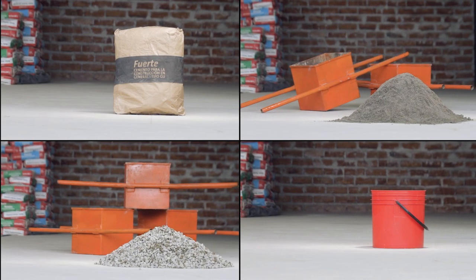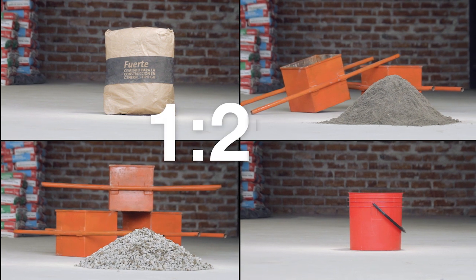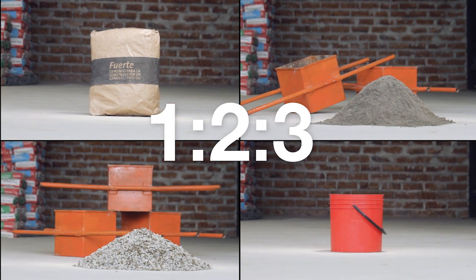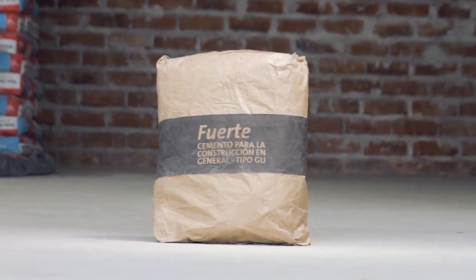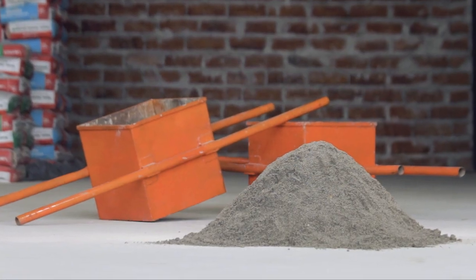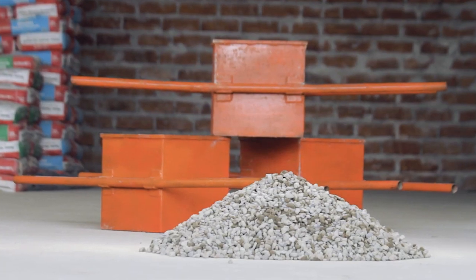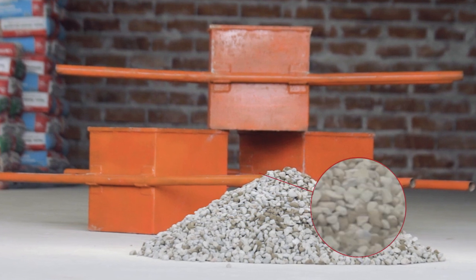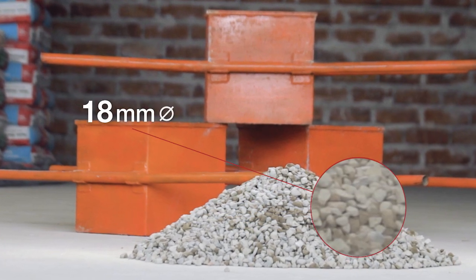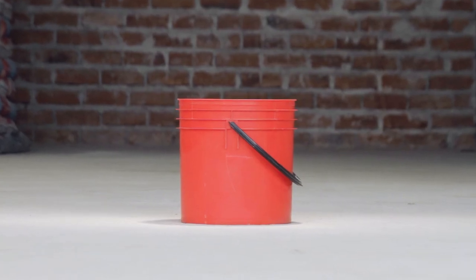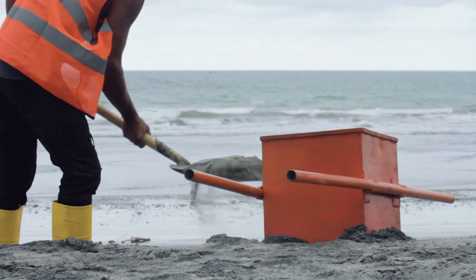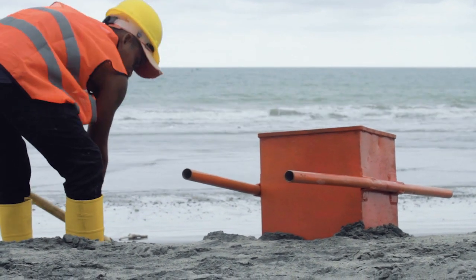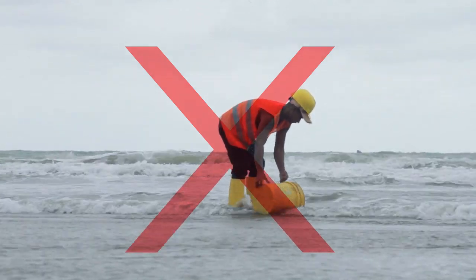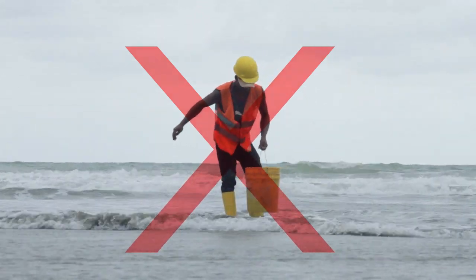Concrete mix. The most commonly used concrete mix is the 1-2-3 mix. That is, one 50 kilogram cement bag, two same volumes of clean, dry sand, three volumes of gravel, in which each stone is maximum 18 millimeters in diameter, and 35 liters of clean water. Beach sand or seawater must never be used because the salt corrodes the steel reinforcements and damages the concrete.